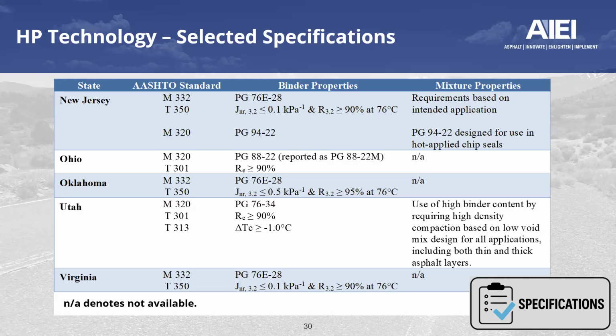I will say that it is a premium mix. And whether we're talking MSCR recovery or elastic recovery, 90 is the number that seems to rise to the surface, no pun intended. If your experience indicates that allowing a 75% recovery still gets you the performance characteristics that you're seeking, then I'm not going to argue against it. But thus far, 90 has been the number that has been settled upon, perhaps because we're conservative engineers, but the performance is indicating that that's a good value.